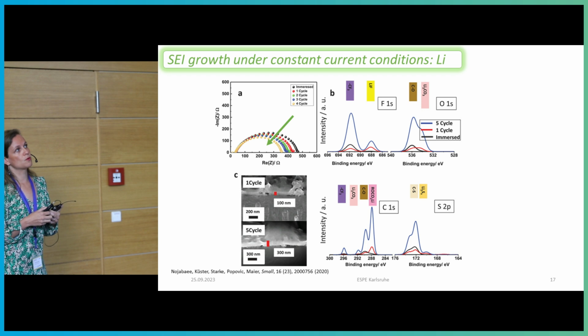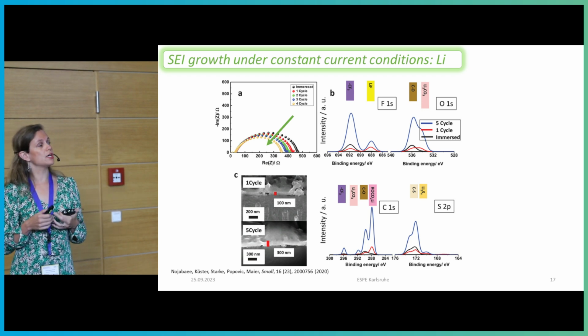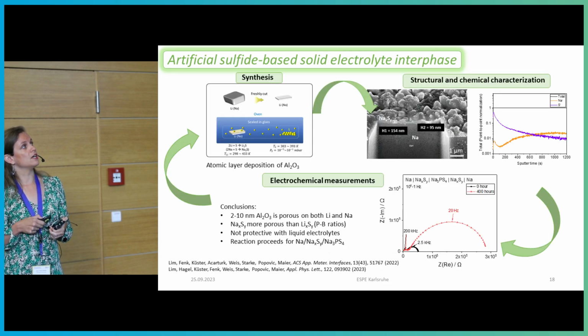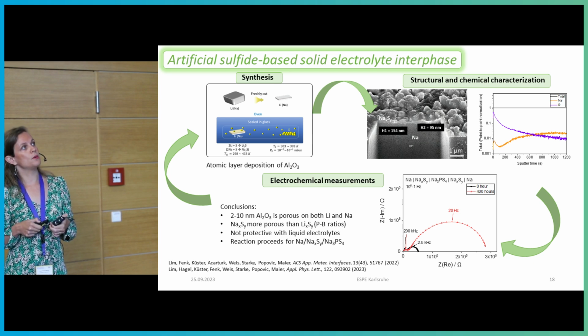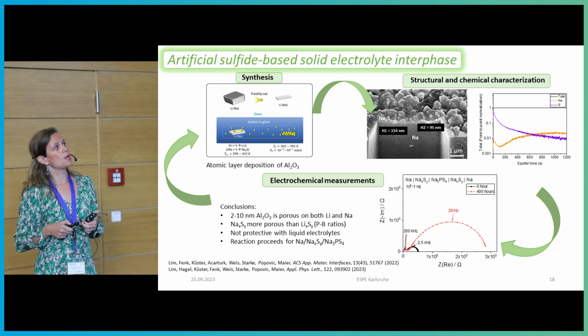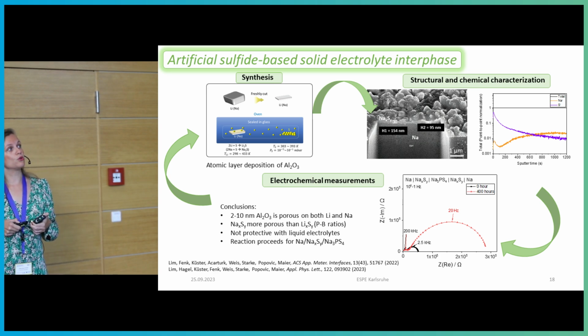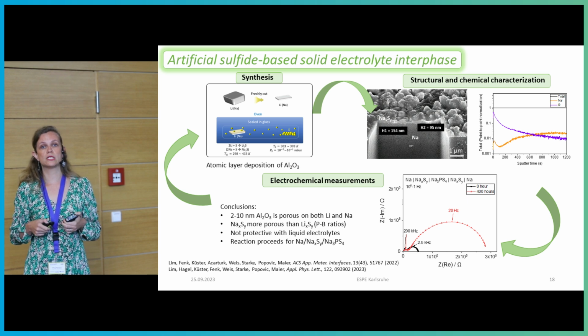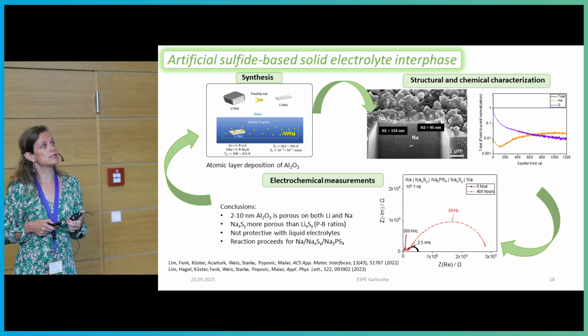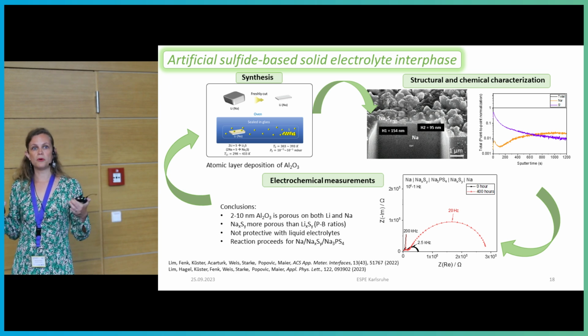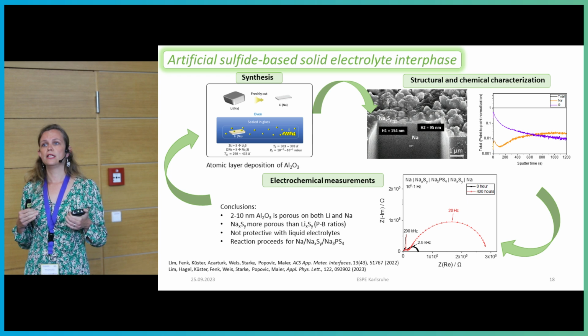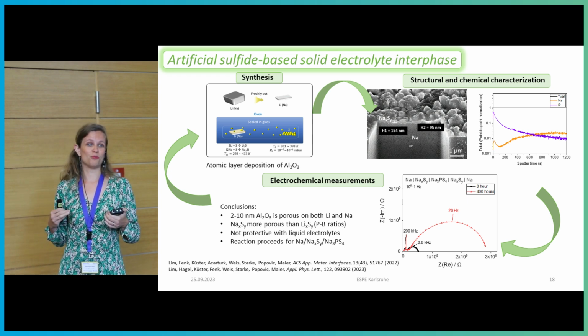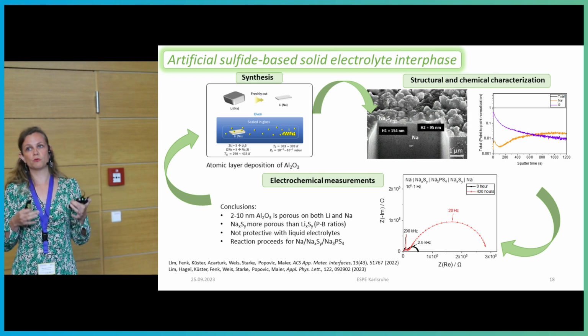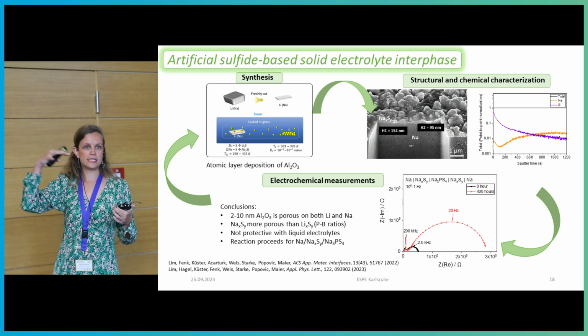And then I said that it's maybe sometimes very useful to try to make artificial SEIs. We tried that too, both with atomic layer deposition of aluminum oxide, but also with this kind of gas-solid reactions where we make sulfides on the surface. But unfortunately, both lithium and sodium sulfides were not actually passivating. So we see the impedance growth at this interface, both in liquid and solid state cells. And we believe that this is related to the Pilling-Bedworth ratio. So in principle, the Pilling-Bedworth ratios tell us that no material can be dense on top of lithium and sodium. So we will always get some porosity, and it's always a kinetic question: when will this liquid or solid penetrate through them?